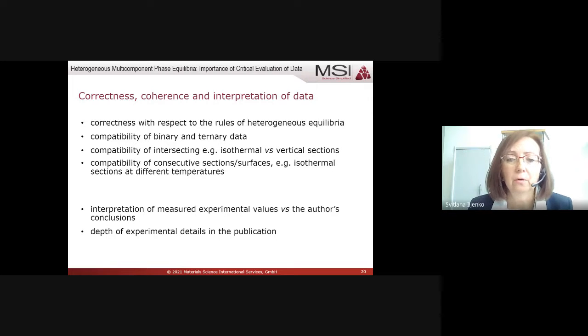Also, we check compatibility of intersecting sections like isothermal and vertical sections. We check compatibility of consecutive sections or surfaces. For example, isothermal sections at different temperatures, whether they indeed match with each other in a way that is feasible. If within 1 degree Celsius a phase transformation would happen, this most likely is unlikely, let me say. Or we check compatibility of the liquidus and solidus surfaces. We check interpretation of measured experimental values against the conclusions of the authors of the original publications.